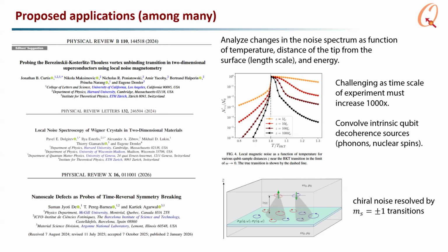It's just how close you can get the NV center, and you can't create these NV centers exactly at the surface of the diamond. The diamond has a reconstructed surface with dangling bonds, and that's going to decohere the NV center very quickly. But when you do these scanning measurements, it's actually even farther than how deep it's implanted into the diamond, and that's usually due to AFM conditions.